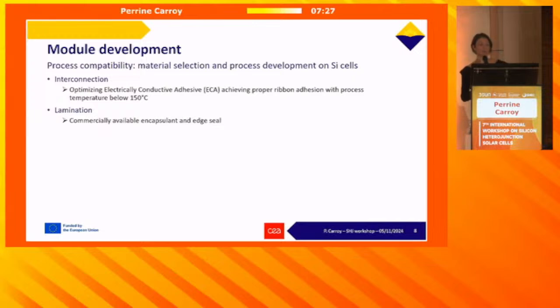Then we want to make modules out of these tandem cells, and of course we want to still stick to commercially available materials. Of course we had to adapt the process to make it compatible with the perovskite, so in particular keep the temperatures low. So for the interconnection we chose electrically conductive adhesive to achieve proper ribbon adhesion, and we worked out a process that would keep the temperature below 150 degrees. And for lamination, we also purchased a commercially available encapsulant and edge sealant.